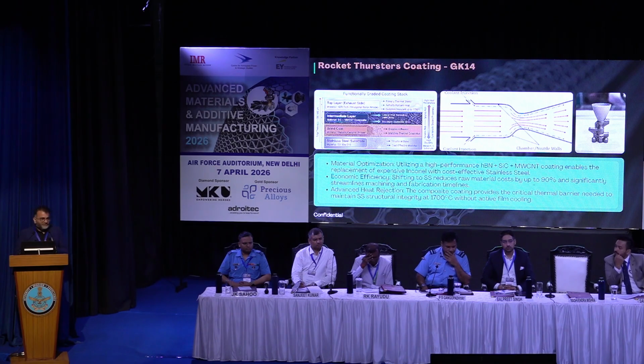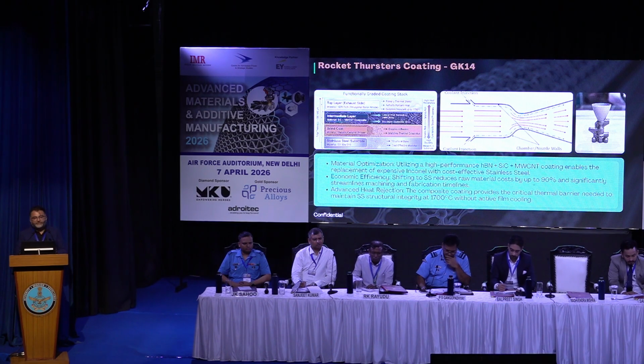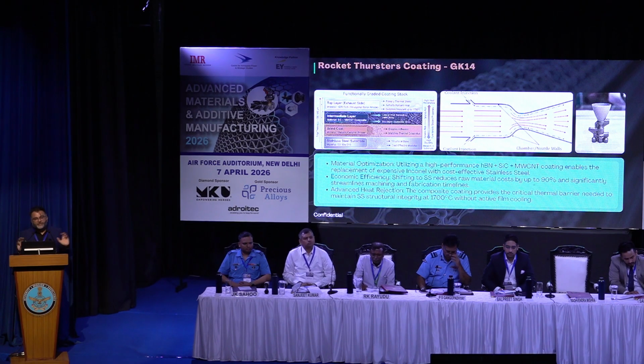So we developed one coating. If you see the thruster of the rocket, which is the third drawing, it uses film cooling, which is the second diagram, where we lose around 3% of efficiency, and we incorporate very complicated designs. Because of this, the thruster usually uses inconel or far superior materials, sometimes hastelloy. By using stainless steel and a hexagonal boron nitride coating mixed properly with silicon carbide and multi-wall carbon nanotubes, we can go up to 2000 degrees Celsius. It can sustain that, you don't have friction because of the hot gases which are going through, and multi-wall carbon nanotubes give you even heating across the surface.